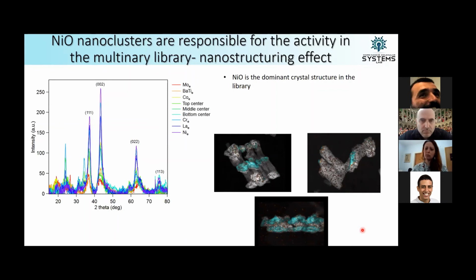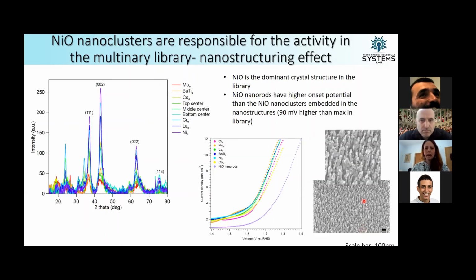And then what we decided to do was synthesize just nickel oxide nanorods in the same system without using this gradient flux. And you can see that these rods are actually composed of small nickel oxide particles. So this is the LSV for these nickel oxide rods, and it's actually much higher than for the whole library. So this means that we have higher overpotentials when we're just using nickel oxide, but when nickel oxide is placed inside these nanostructures in these slightly different chemical environments, it has much higher activity towards OER, reduced by even 90 millivolts. So it's a really large reduction for just changing the structure of the nickel oxide clusters within the nanoshapes.